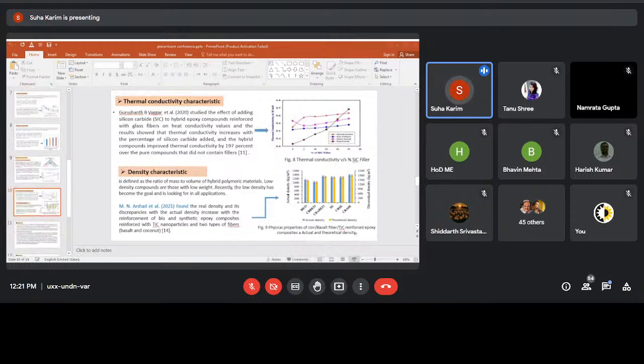Related to another study in 2020, in the same study about the thermal conductivity, they found that silicon carbide with glass fiber and epoxy matrix will increase the thermal conductivity, as we see in figure 8.